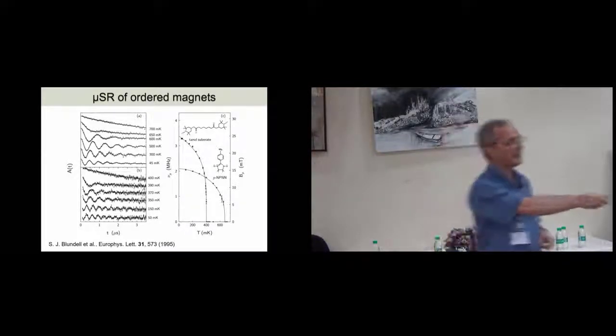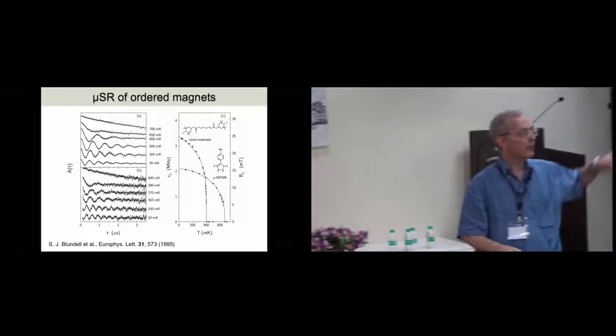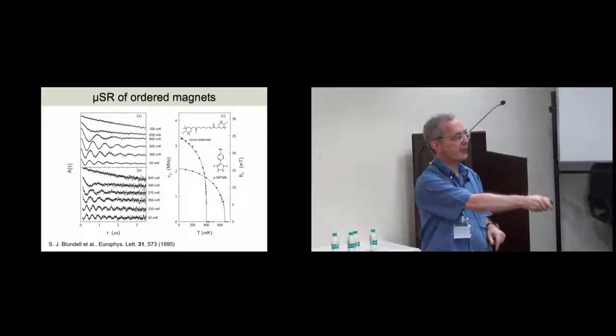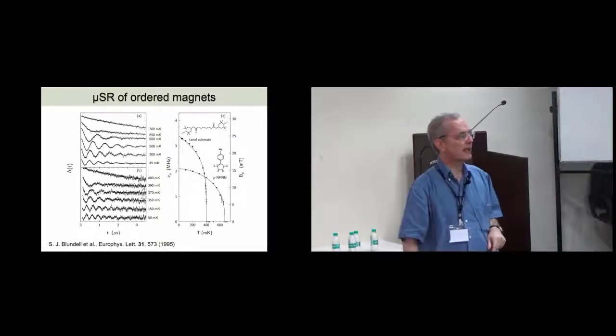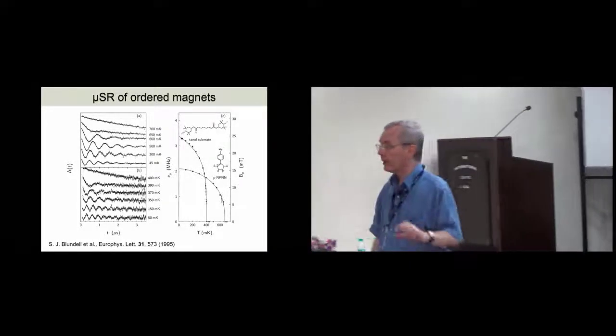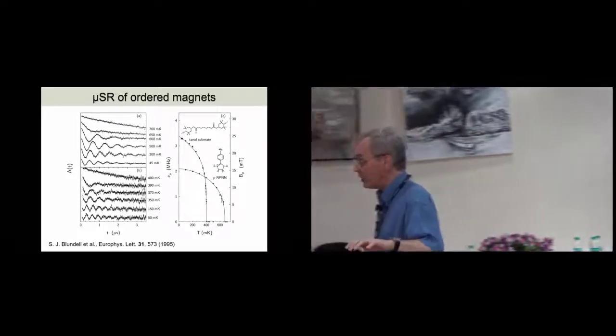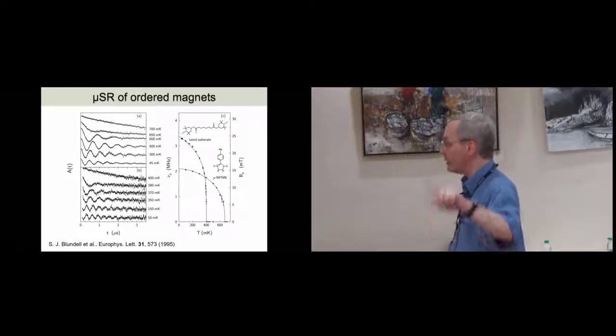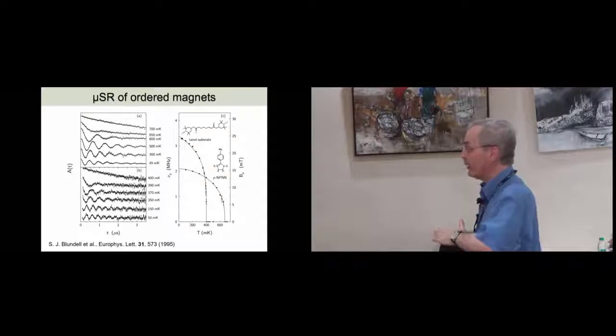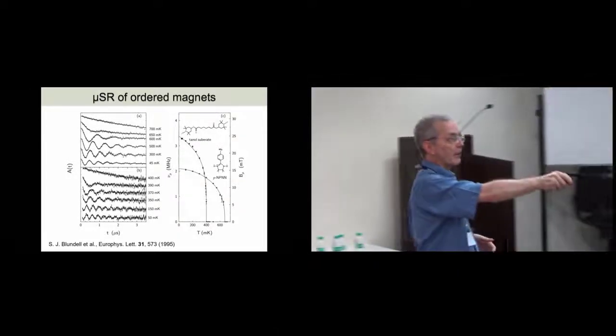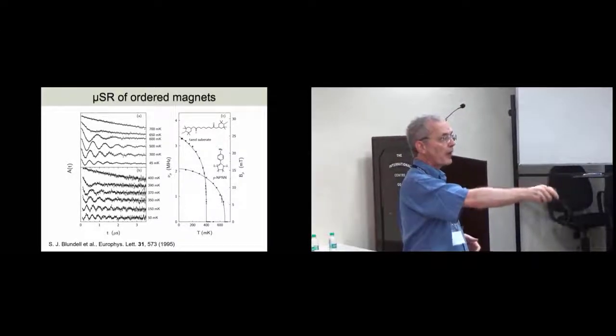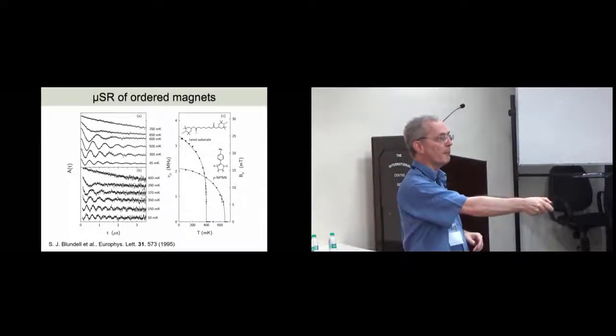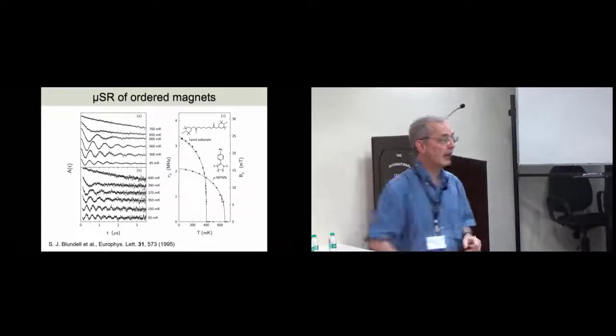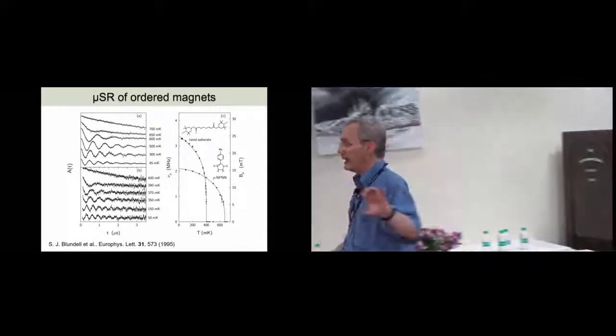And what you can do with these data is you can fit a frequency. You can then plot the frequency as a function of temperature. And this shows you how the frequency for these two samples varies as a function of temperature. But remember the gyromagnetic ratio. That tells you how many megahertz per Tesla. So you can immediately convert megahertz into Tesla. So on the right axis here, I've got magnetic field. So we now have a measurement, an excellent measurement, of magnetic field inside the sample at the muon site in millitesla.